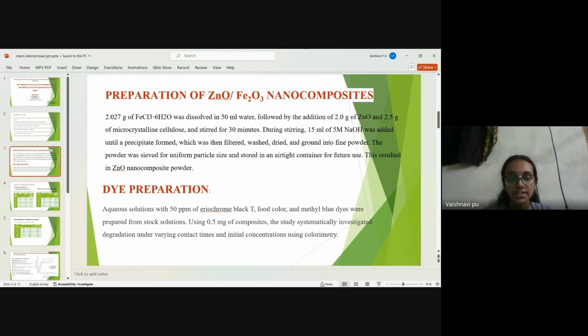So this powder was tested with the dyes that we have prepared. The dyes were prepared as aqueous solutions with 50 ppm of eriochrome black T, food color, and methylene blue dyes. They were prepared from the stock solution using 0.5 milligram of the composites. The study systematically investigated degradation under varying contact time and initial concentrations using colorimetry.